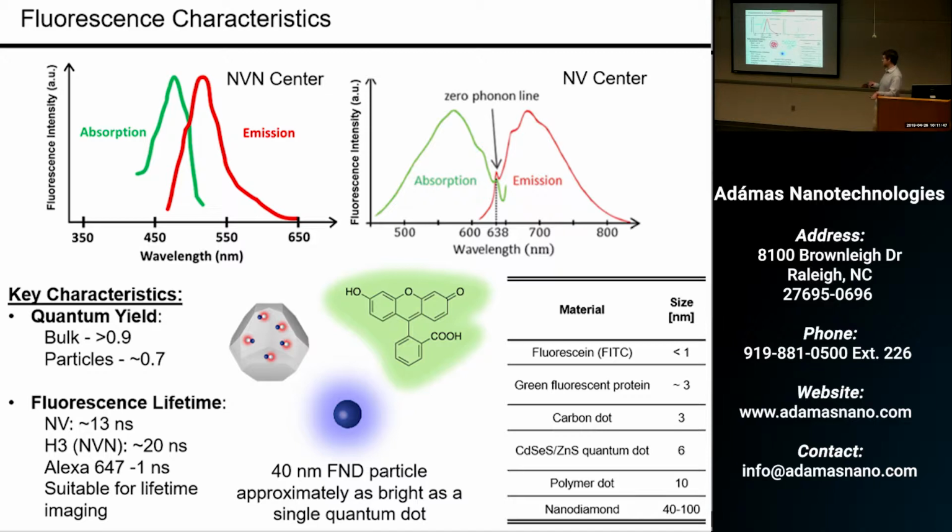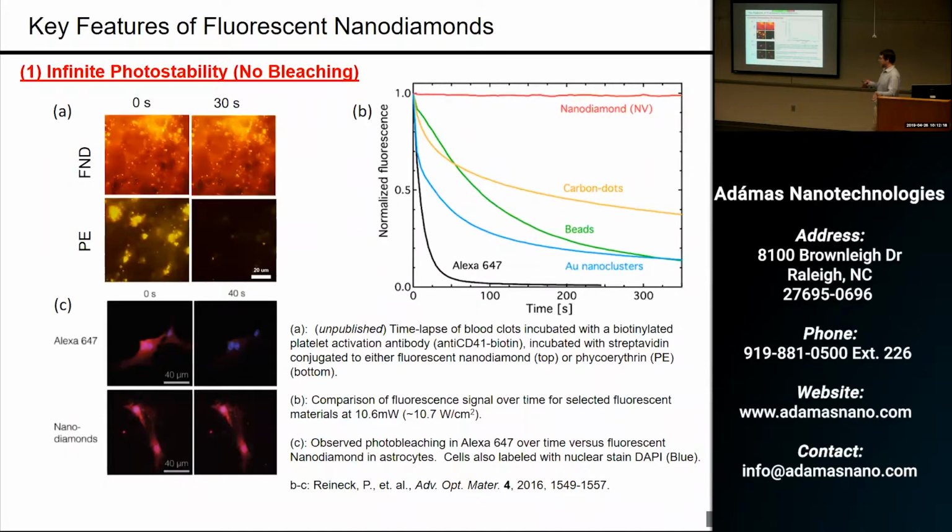And I did want to reemphasize the nature of this fluorescence. It's not that the entire particle itself is fluorescent. The particle has individual fluorescent color centers packed within this single particle, which all fluoresce, and then you get your fluorescence from the particle in that way. Quantum dots or polymer dots emit uniformly, and fluorescent dyes, for example, emit as molecular fluorescence.